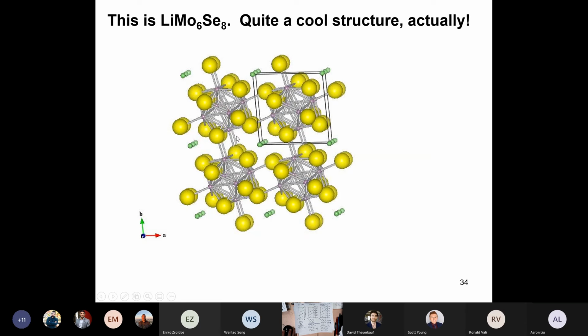And the reason that this structure is interesting is because when you work between no lithium and 1 lithium, the lithiums are so far apart that one lithium doesn't really notice the other one. Their Coulomb repulsion is incredibly tiny. So you can study a system where you can add lithium and they don't interact with one another at all.